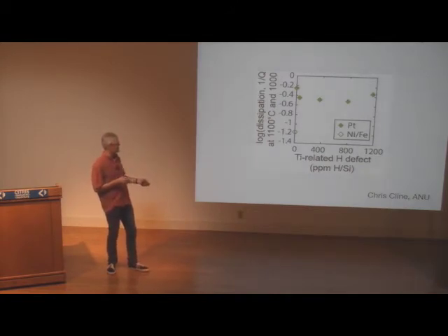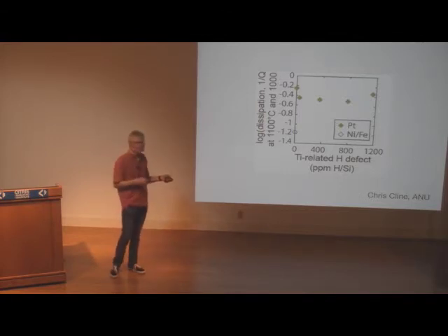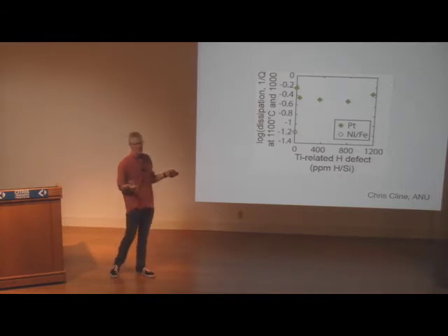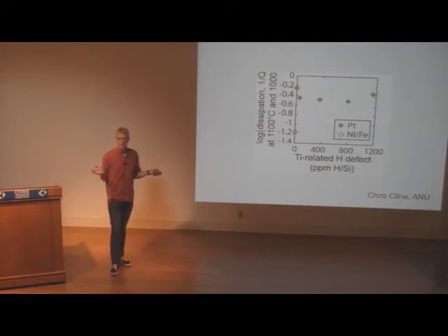Basically you can see here, for the rheology, we had a nice linear relationship: as we increase the water content, the strain rate increases. This is not what we observe here seismically. Essentially, we have a null result. We increase the water content, but the dissipation, the energy loss, stays exactly constant. So to first order, water has no effect on seismic properties.